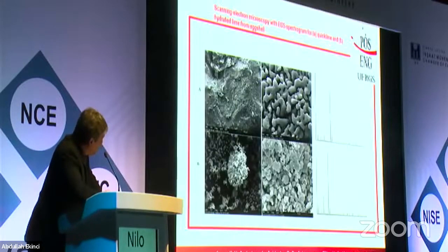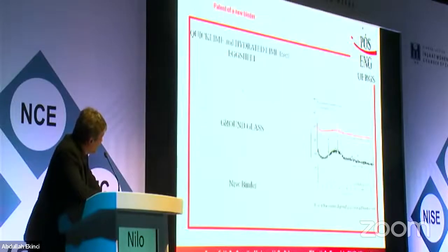Here is a paper in which we produce, for example, a very good lime, much better than the commercial one, using eggshell, for example, at this moment, burning it. And so we produce slaked and unslaked lime with a fantastic amount of calcium oxide and such and so, which is quite interesting.